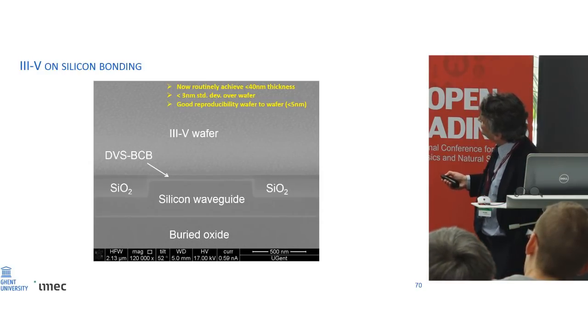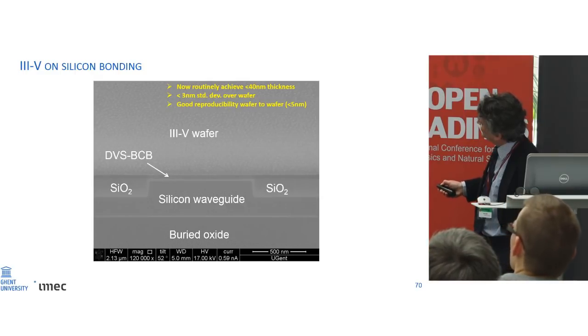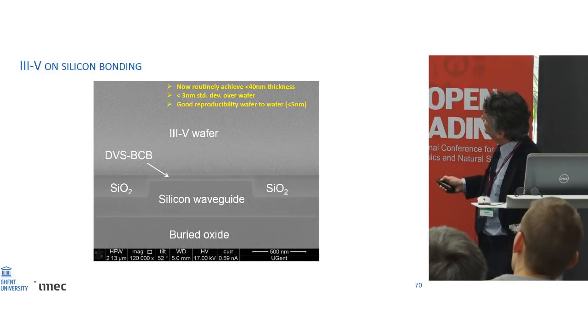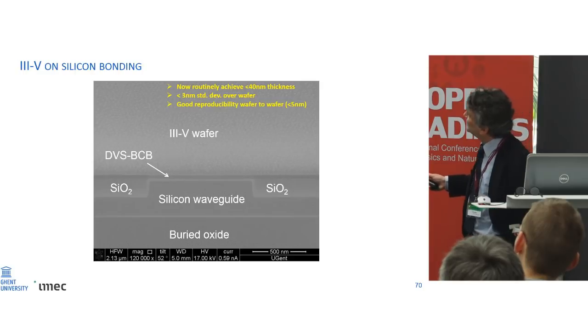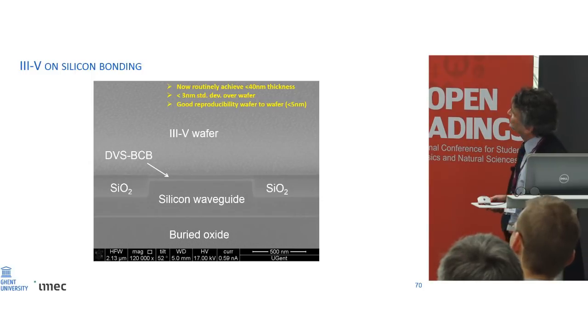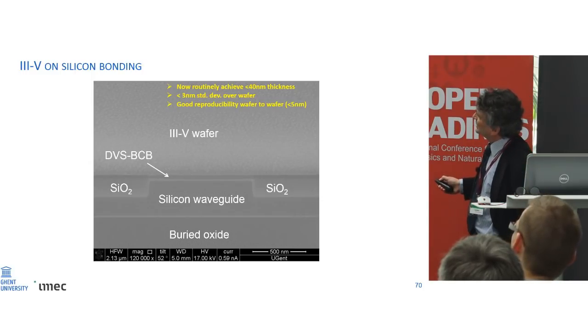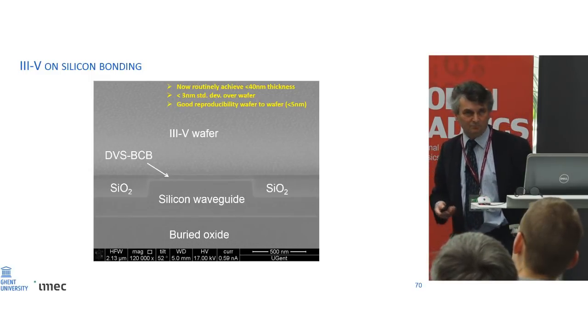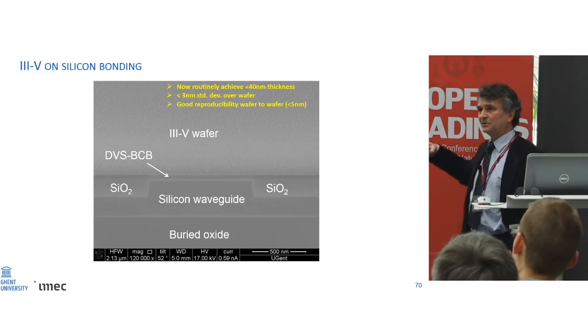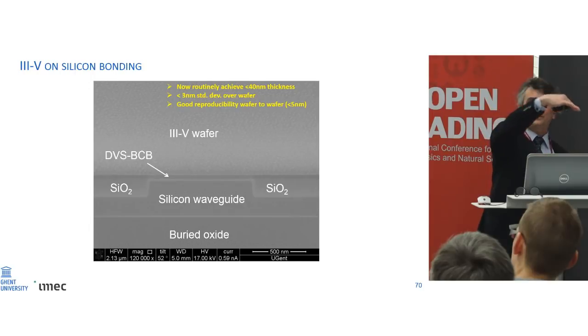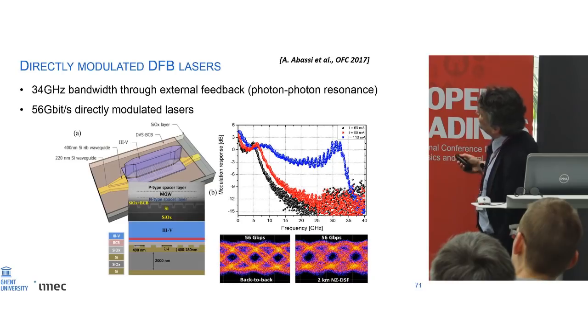Here, for example, you see a cross-section of, indeed, you recognize here again a silicon waveguide, so light is propagating normal to the screen here. Here the III-V starts. In this case, we use bonding through an agent, BCB. It's like a glue, you could say, but then a very thin layer of glue because this layer is perhaps 10 or 20 nanometers thick. And again, as I mentioned earlier, if light is propagating in the silicon waveguide, there is this evanescent tail that extends into the III-V and picks up gain. And you can also make light couple from the silicon layer to the III-V layer and back. Just a few examples of things we did with that.